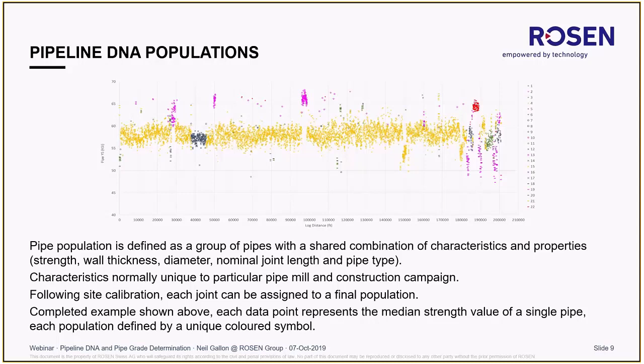And following calibration, we can assign each joint to a final population. So the graph above is the same as the previous one, but we have gone through the population process and we have split up that original lot of pipes into individual populations. Each color code, or each color code and marker type, identifies a different population. I'm not sure if you can see the legend on the right hand side, but in this particular line we have identified 22 separate populations. So 22 individual combinations of original pipe mill, original grade, original wall thickness, etc., etc.